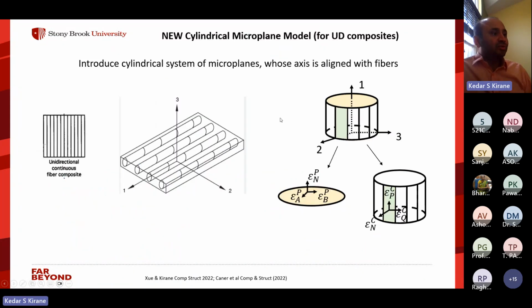So what we did was we developed a new kind of microplane model. It is the cylindrical microplane model. So instead of the sphere, we introduced a cylindrical arrangement of these microplanes. And all of these are imagined microplanes at a given material point. Okay. So if you imagine one unidirectional lamina, which has fibers running in one direction, we assume that a cylindrical system of microplanes exists, which essentially consists of several planes along the surface of the cylinder and one plane which is lateral, okay, like this.